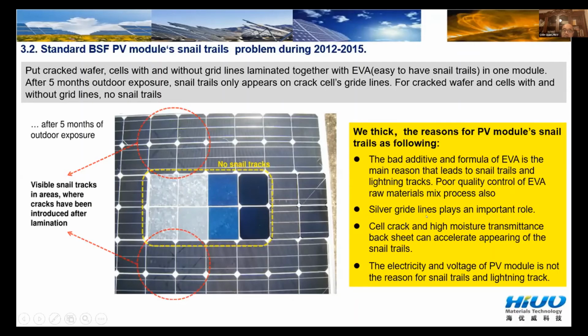The second one is that the silver grid lines play an important role. Without silver grid, it will not happen. And cracks and high moisture transmittance backsheet can accelerate the appearance of snail trails. That is why you can see a lot of snail trails come together with cracks, because they can accelerate it, but it's not the reason. The reason is the EVA itself, okay? So the electricity and voltage of the PV module is not the reason. Even some modules that do not work, put into the package, still have snail trails. It's one kind of chemical corrosion, okay? Chemical corrosion. That is the whole reason for snail trails, okay?